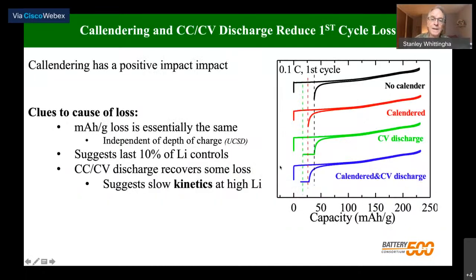What did have an effect was calendaring. Let me explain what this is. When you make a lithium battery, you coat the active material onto an aluminum sheet as a paste, you dry it, then you put it between rollers and press it, and this is what the calendaring process is. So you can see the black curve here is no calendaring. If we calendar it, you can see it's got a little bit better.